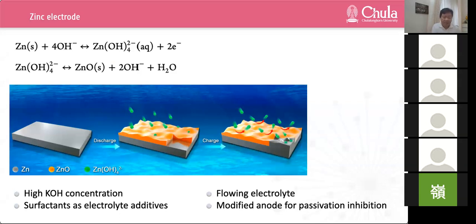Well, the above surfactants can significantly suppress the passivation and corrosion of the zinc anode in a dilute alkaline electrolyte. Because the absorbed surfactant molecule can prevent contact between water and the anode. Some studies have suggested that anionic surfactants outperform cationic surfactants in enhancing the cycle life of the batteries, because the negatively charged polar group of SDBS coordinate to zinc ions at the anode surface, leading to the generation of small zinc oxide particles that effectively inhibit the growth of the passivation layer.